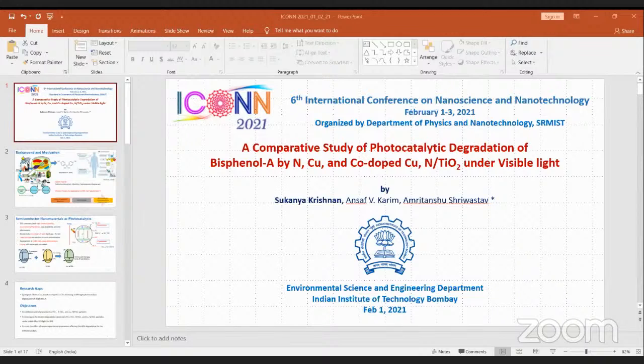Below 200. Okay. So why I'm telling you that with the doping concept, at least you can try for a maximum of 5 to 10%. If you do too much doping, then segregation happens, that is not really good. It messes up the system. Maybe try to do less than 5 to 10%. That will be good. Okay.